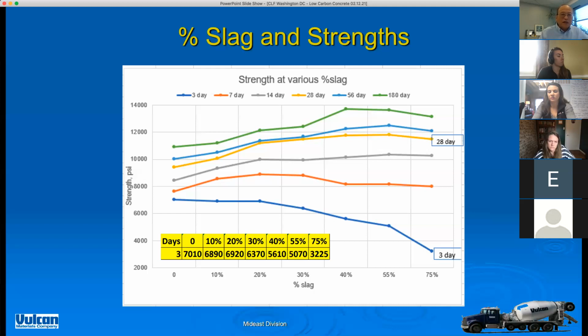But as you look at the other graph, the red graph, that's a 7-day. Then the gray one is 14-day, and then 28-day strength. Once you get past the 3-day strength, you see the strength start to catch up. And by the time you get to 28 days, you actually get an increase in strength when you have more slag in a mix. So it's very interesting. But as you can see there, the optimum amount is right there between 40 to 55%. Adding more actually starts to diminish the strength development a little bit. So you do sacrifice some strength when you go to higher amounts of slag cement. Next slide, please.